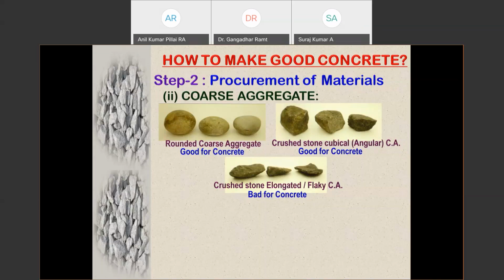But if we have elongated or flaky material in our concrete, under loading, the first thing that it will do is break into pieces because of compressive load, and because of elongated and flaky shape, it will easily be crushed under loading. And once it is crushed, cracks are formed, and under further loading there will be stress concentration and propagation of cracks, and early failure of the concrete system will take place. Hence, this material should not be used.